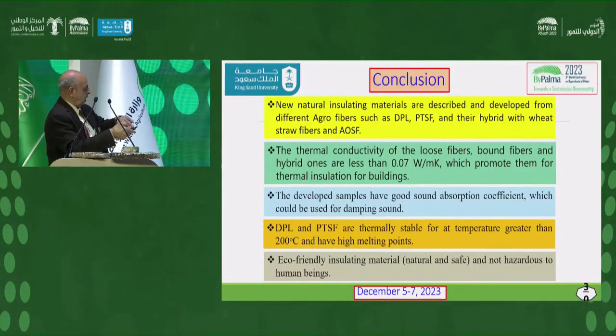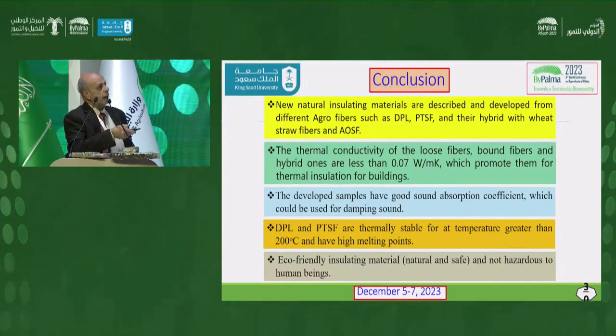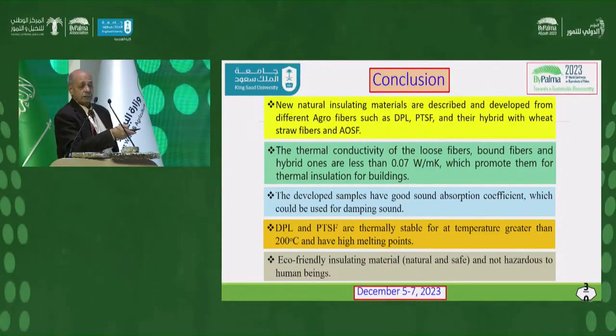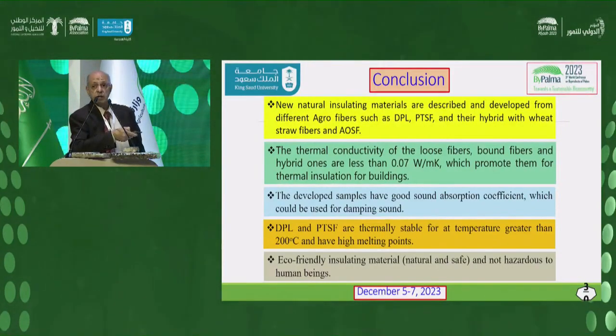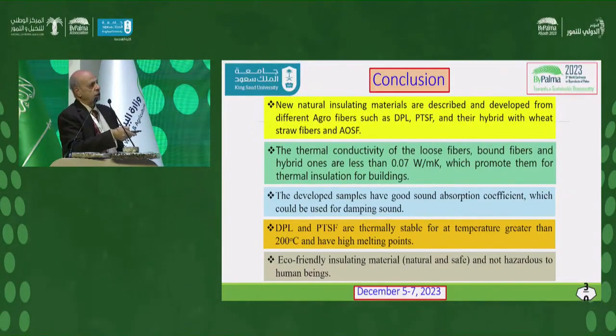So, conclusion, new natural insulating materials are described and developed from different agrofibers such as date palm leaf, palm tree surface fiber, and their hybrid with wheat straw fiber and apple of sodom fiber. Thermal conductivity of loose fiber, bound fibers, and hybrid ones are less than 0.07, which is very good to be considered for sound insulation and thermal insulation. The developed samples have good sound absorption coefficient.